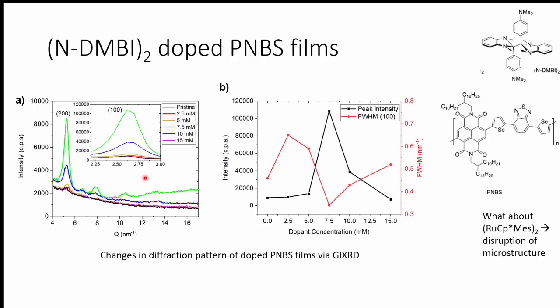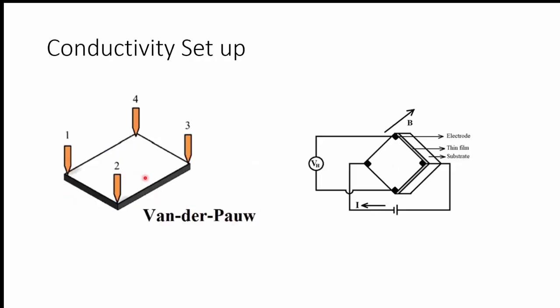The reason for that is that such a bulky dopant with a large volume trying to diffuse in is messing up all of the stacking that you already established in your polymer film. So although it's doping it, it is not maintaining the structural order, and that we know is not good for conductivity. And actually, when we measured the conductivity, we did not get conductive films with the ruthenium dimer. Although it was doped, it was not conductive because of this structural disorder, because the charges could not move from one place to the other for us to measure how conductive they are.